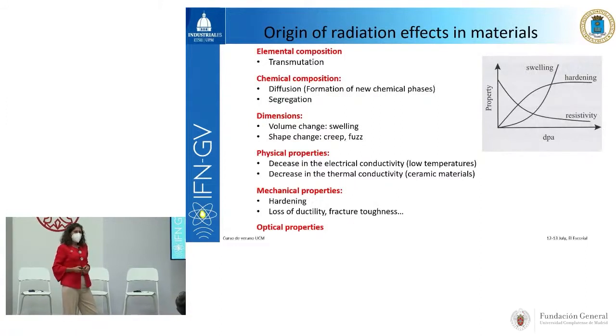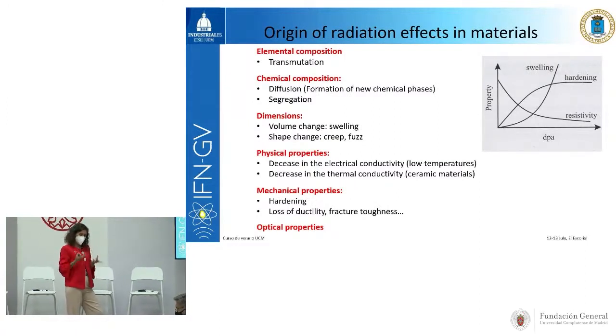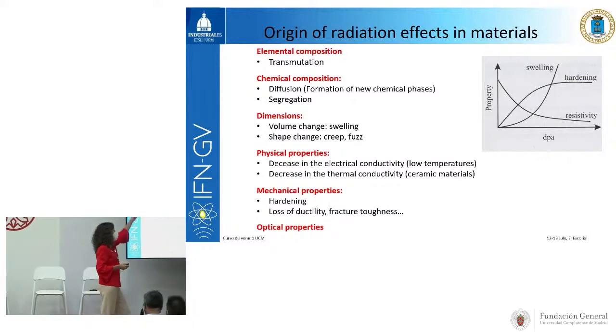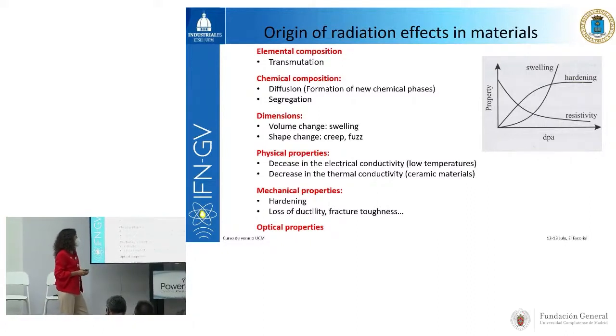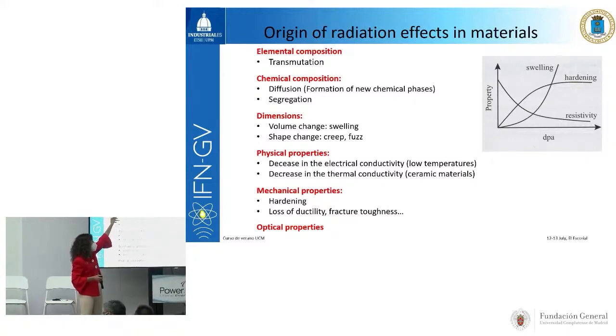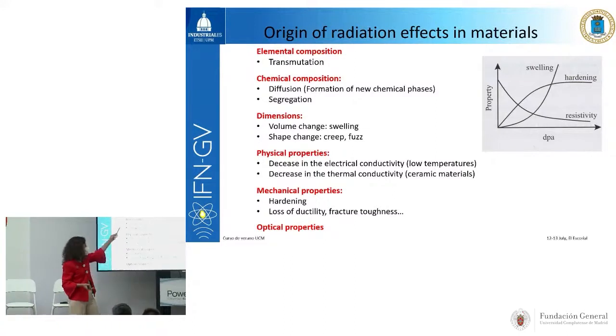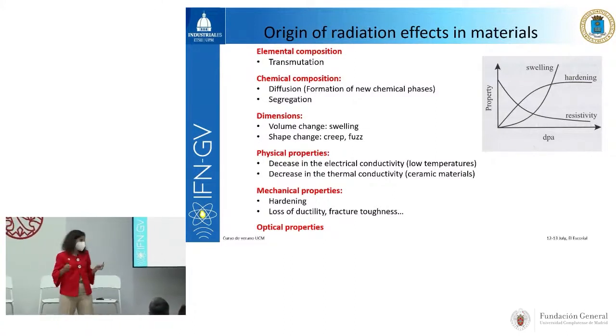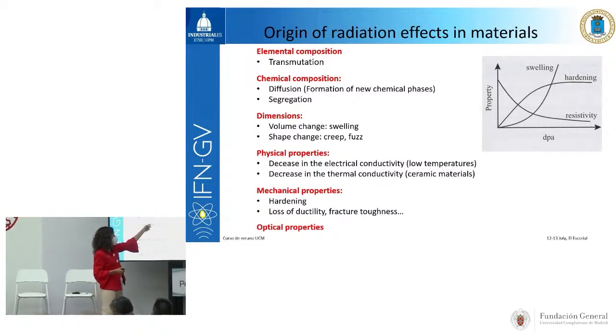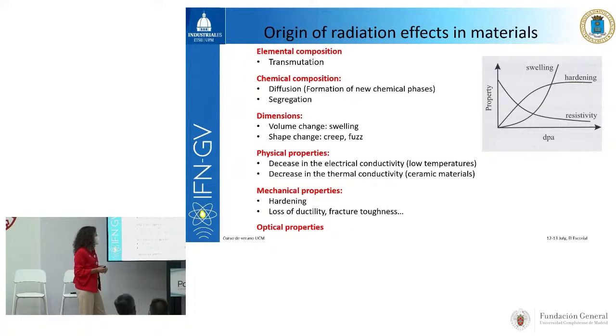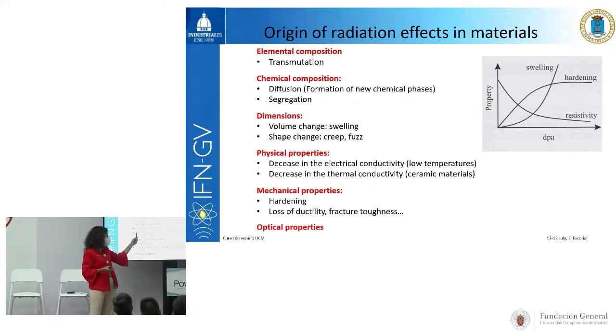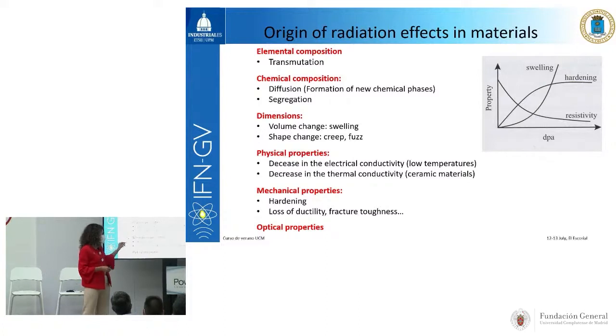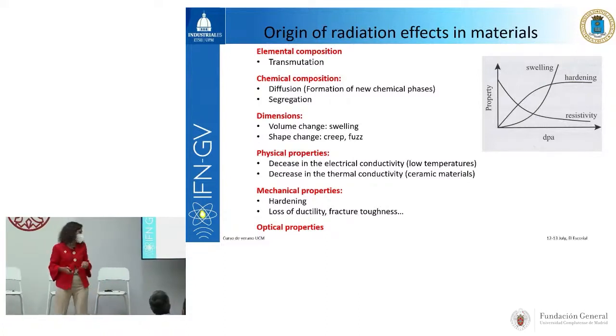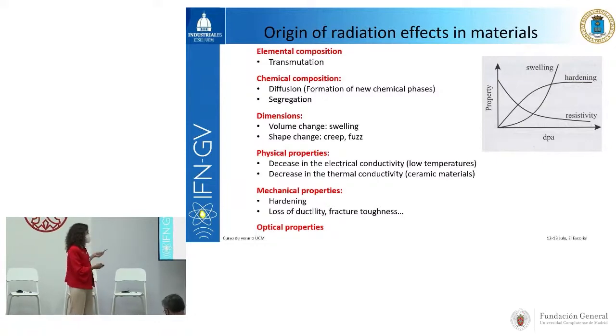So what are these very specific defects producing in the macroscopic properties of the sample? What are the macroscopic changes we can observe? Basically, transmutation produces changes in the elemental composition. Then the chemical composition is also modified by diffusion, so the formation of new chemical phases and segregation. The volume also changes, for example by swelling, and shape changes, creep or fuzz, and the physical properties. Typically, the electrical conductivity decreases and the thermal conductivity also decreases. And they also produce, as Angel Ibarra was telling yesterday, changes in the mechanical properties, hardening and loss of ductility, and so on, and in the optical properties. So this is what we need to characterize.